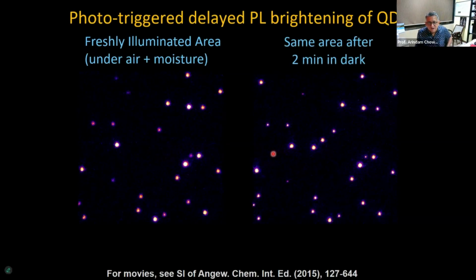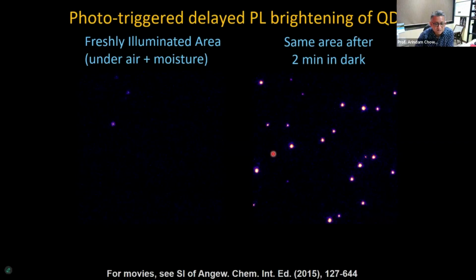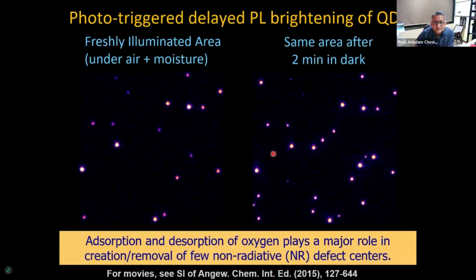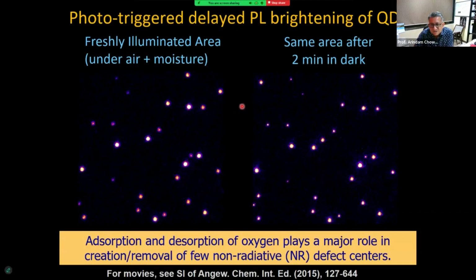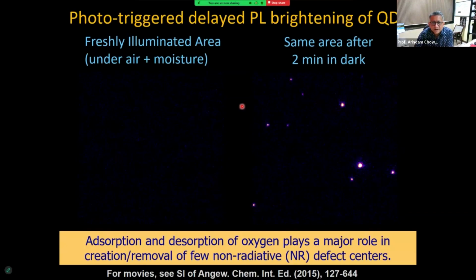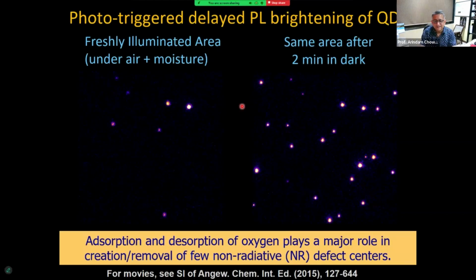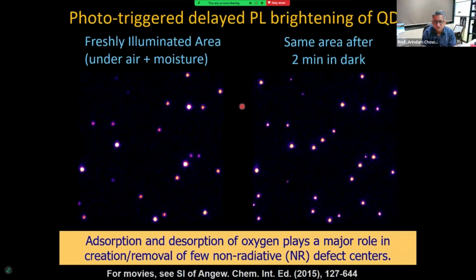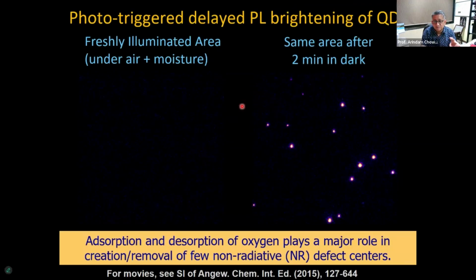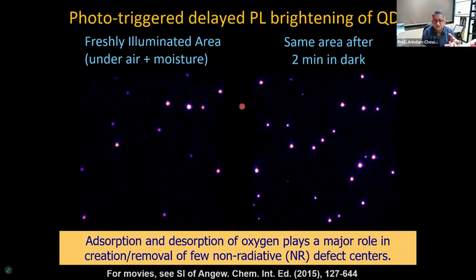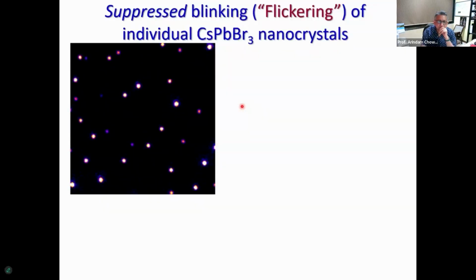This is under air and moisture, and we can repeat this experiment by keeping it in the dark and then redoing the measurement. We see a similar behavior, which tells us that there is something to do with the atmospheric constituents absorbing on these nanocrystals, and they can affect what kind of defects. Their adsorption and desorption can basically create or remove defects, and that can change its emission properties.